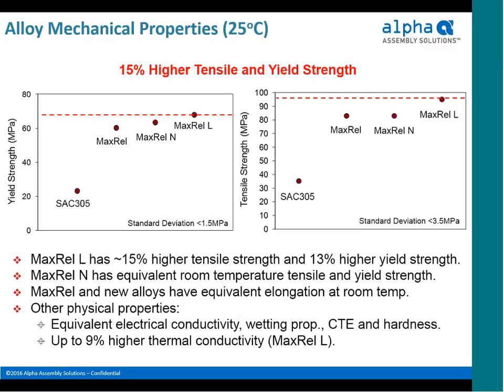In both these cases, you can see that this material family of alloys have much higher yield and tensile strengths, and they're designed for use in service environments such as, say, underhood automotive, where SAC 305 just doesn't have quite the robustness it needs for the service environment.